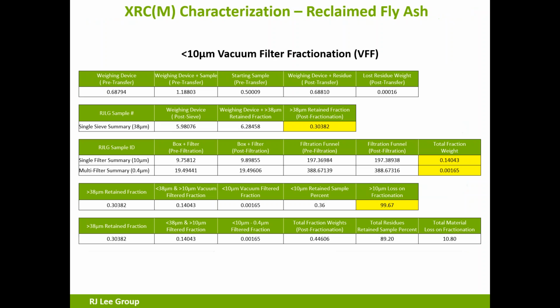And this is going to be a very small amount of material. In fact, if you look at this slide, you'll see the weights: we started with 0.5 grams, we got 0.3 grams greater than 38, we got 0.14 grams between 10 and 38, and 0.00165, or 1.6 milligrams, between 0.4 and 10. Our loss on fractionation is 99.67%. In other words, the vast majority of this material is not respirable.